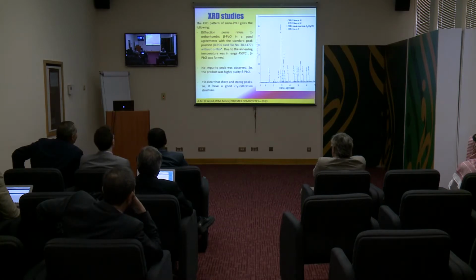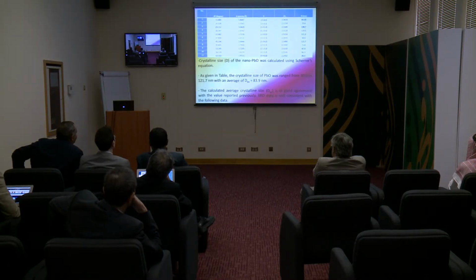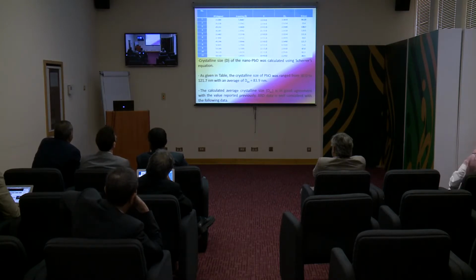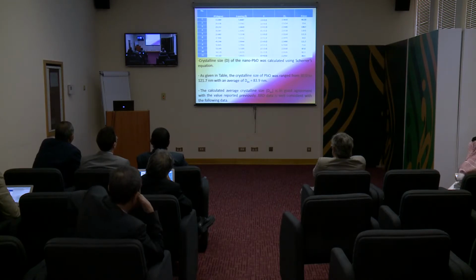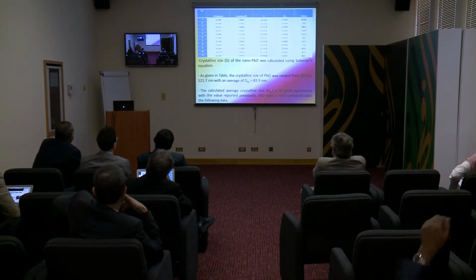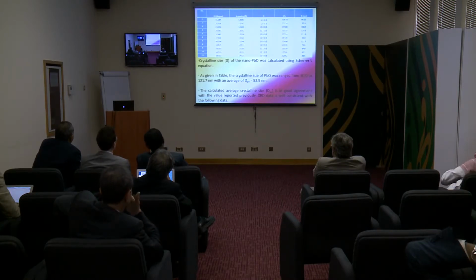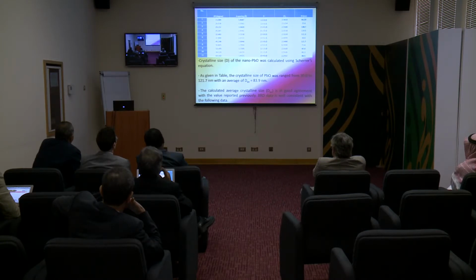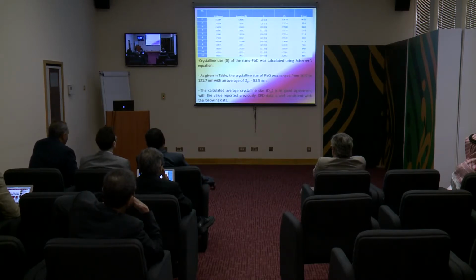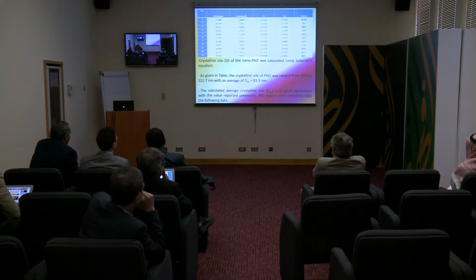It is clear from the sharp and strong peaks that it has a good crystallization structure of beta lead oxide. From the X-ray diffraction data, we used the Scherrer equation to calculate the crystal size of the particles, as shown in the table. The crystalline size of beta lead oxide ranged from 30 to 121 nanometers with an average of 83.9 nanometers. The calculated average crystalline size of beta lead oxide is in good agreement with the value reported before. The X-ray diffraction data is well consistent with the following data.